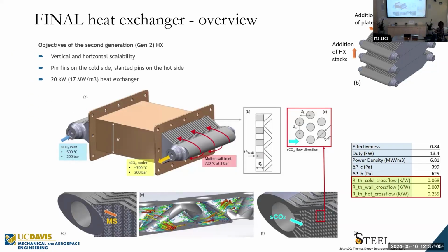So here I will start with a conclusion, what the final heat exchanger that we designed looks like. And you can see it over there. So in a heat exchanger, we have two fluids, right? You have two sides, a hot side and a cold side. On the cold side, we have SCO2 that enters at 500 Celsius, 200 bar. And on the hot side, we have molten salt that enters at 720 C and atmospheric pressure. The two fluids exchange heat, and ultimately, we want to design the heat exchanger such that the outlet temperature of CO2 is about 700 Celsius and above. We also want to minimize the pressure drop from inlet to outlet.